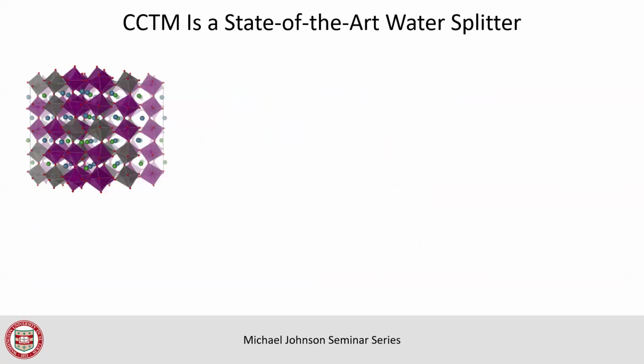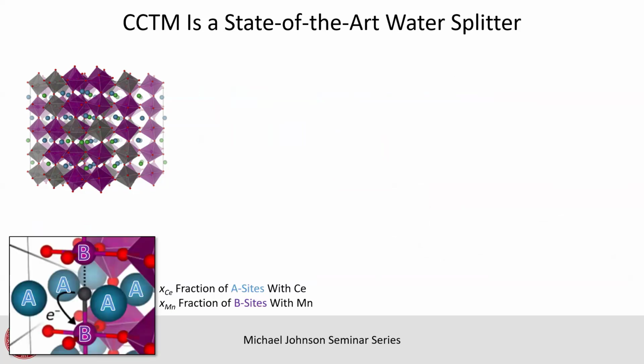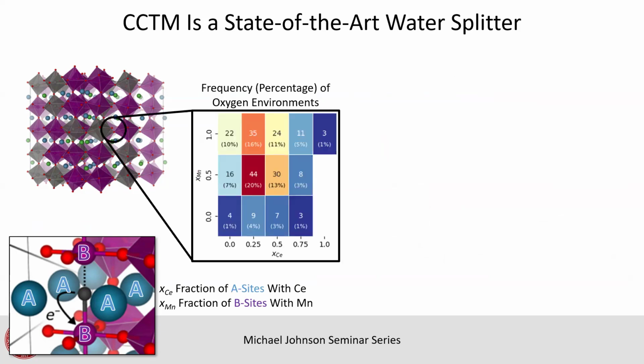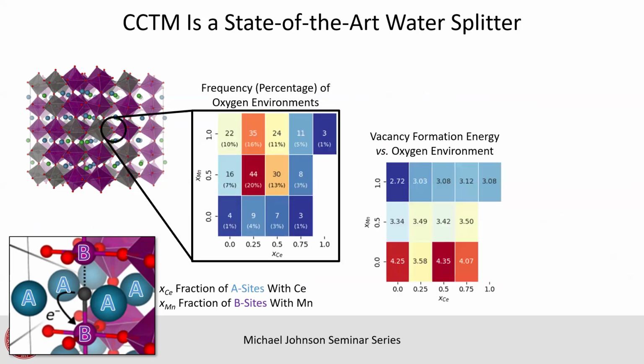Number two aspect is, can it actually form these defects with the right energy process? The way we think about that is, if there's an oxygen and you can see there, it's turned black, that means it's now a vacancy, a missing atom. If you calculate all the features associated with different environments, you can ultimately make predictions on this value depending on which oxygen you are in the crystal. As you can imagine, based on the mixture here, you might have different oxygens in different environments.